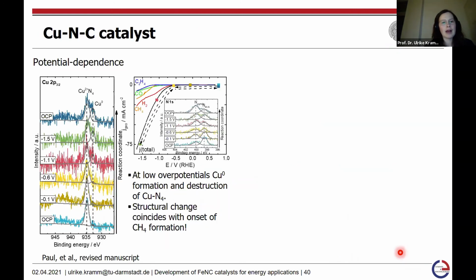So I would like to focus here on the postmortem XPS results. So here we have the current density as a function of potential for the Cu-N-C catalyst material. So the black closed curve here is the as-measured current density, and the squares here represent the different points when the electrode was extracted for the postmortem XPS.